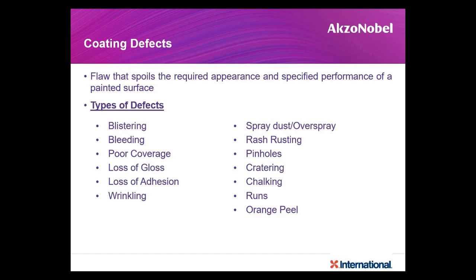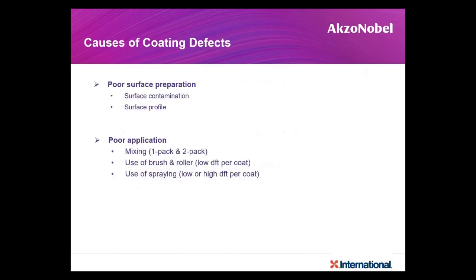Types of defects: blistering, bleeding, poor coverage, loss of gloss, loss of adhesion, wrinkling, all these things will happen. Overspray, dry spray. You can find rash rusting because of poor coverage, pinholes, cratering, chalking. You could find sags and runs, sometimes a rough orange peel-like finish. So you have to observe very closely in order to detect a defect. Special eyes are required for this. In the sense, experience is what I say. Everybody can detect once experience is there.